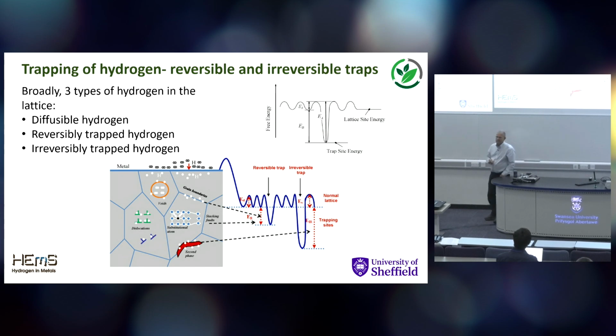We broadly categorize the hydrogen into three categories. The first is the diffusible hydrogen, which is just hydrogen that can simply move through the material. So if you charge the steel with hydrogen, then it will gradually diffuse out of the material over time, and that's the diffusible part. What we're particularly interested in are the reversibly trapped hydrogen and the irreversibly trapped hydrogen.